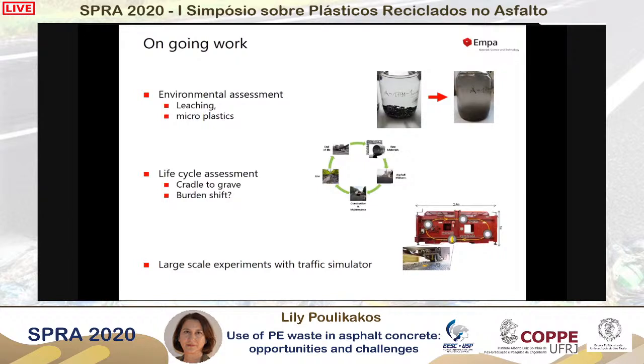Now we have also various things that are ongoing. For example, the very important area of environmental assessment. We are performing leaching tests. Here there's an image from a mixture that had crumb rubber in it, and so we're looking at what leaches out in the water. And in this case, we would like to also look at microplastics. That's a big topic right now, and also the idea of if our bitumen can keep the microplastics intact and not allow it to leach into the water, that would definitely be an added advantage. So we're cooperating with our colleagues, both at the European and at the international scale through RILEM, and with our colleagues at EMPA to look at this topic.